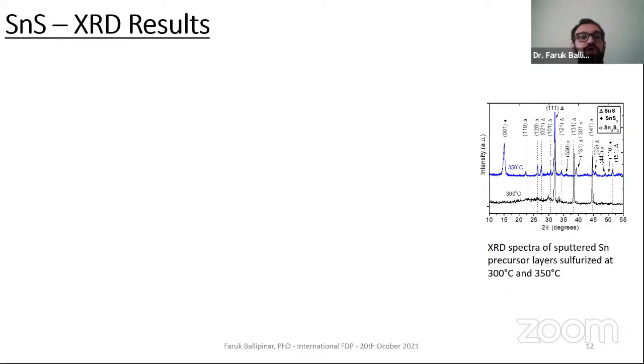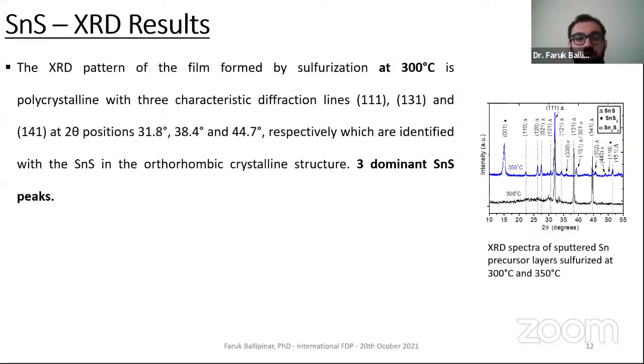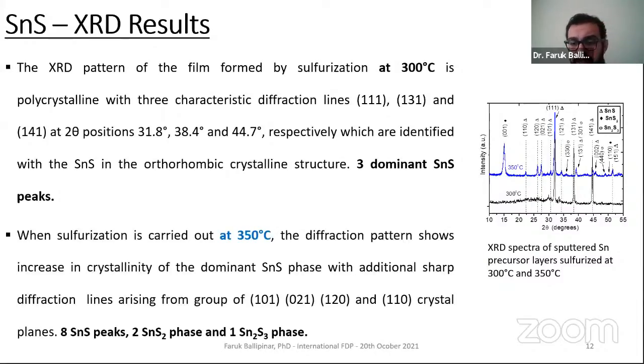Moving to material characterization is a critical step after processing thin film. So we have 3 films: 300, 350 and 400. The XRD characterization was the first one, to identify the phase of the material. Looking at the 300, there are 3 dominant tin sulfide phases, and the blue one shows 350 degree. It has several planes, several phases from other phases as well. But in terms of the number of peaks, it has dominantly tin sulfide phase.